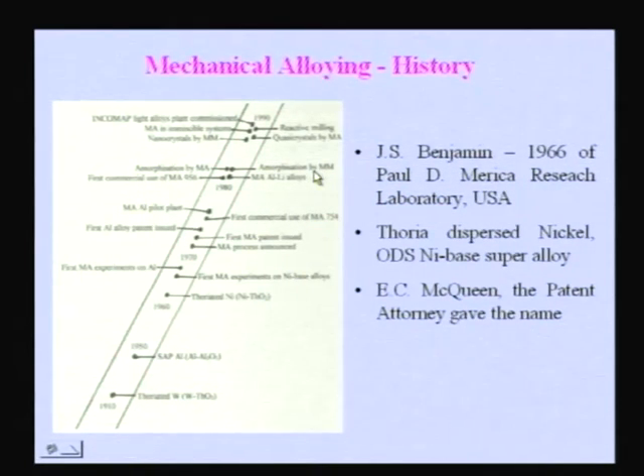What it means is that you take a compound, keep on doing ball milling, and the ordered compound transforms into an amorphous. First it becomes disordered and finally it becomes amorphous. So instead of doing mechanical alloying where you take elements A and B, whenever we take two or three or more than one element and put it into a ball mill and do ball milling, we call it mechanical alloying, because you have individual elements there. But if you take a pre-alloyed powder, that means an alloy which is already made by some means, by melting and casting route, and put that alloy powder into a ball mill and do the ball milling, we just call it mechanical milling.